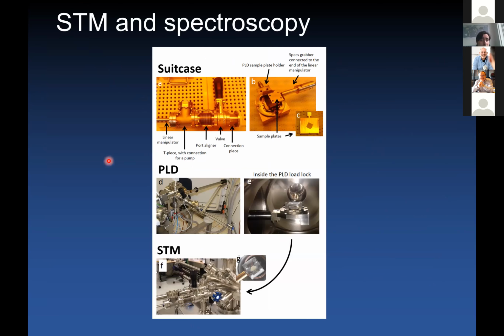And the next step that we took experimentally was to look at the local density of states using STM and STS, so scanning tunneling spectroscopy. So in order to perform these studies, we built a vacuum suitcase in order to transport our films from a PLD chamber to a very nice STM that is available in our department for this type of study without breaking vacuum.